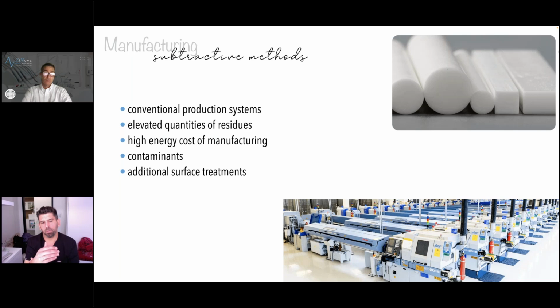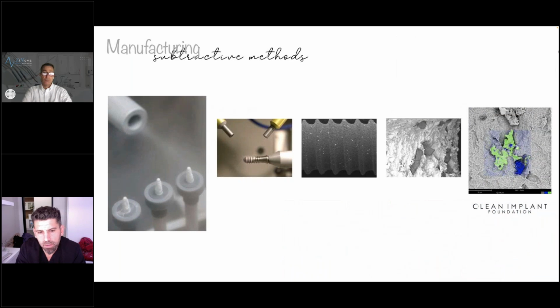And then after that, the material has to undergo additional surface treatments to obtain the rough surface, whether it be sandblasting or acid etching or a combination of these. And we know that these processes can leave residues behind. And this is something that the Clean Implant Foundation has been looking at for years now. This manufacturing process, this subtractive method to create these rough surfaces, can leave these impurities on the surface of the implants.